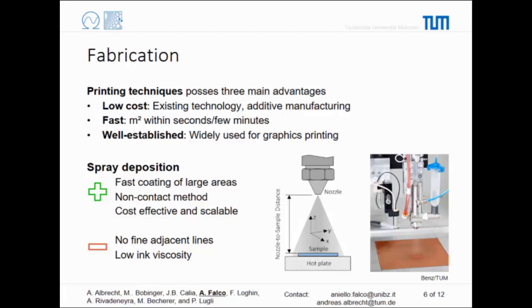Now, it is a coating technique, which means that it is in principle covering the whole substrate, but by using stencils, so shadow masking, we can actually achieve patterns, which is very good, especially in this case for thermocouples, for instance. It is a very fast method, it's very reliable, it's easy to integrate in high throughput technology. We've seen in many fairs that they integrated it also in roll-to-roll facilities.